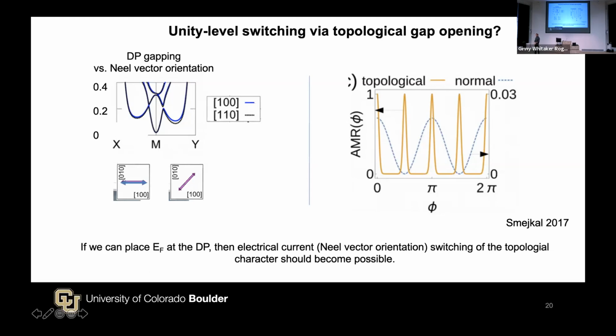From what you're saying, these different layers, does that mean that the controversy over whether the surface of manganese bismuth telluride is gapped or gapless is no longer a controversy? It could be entirely explained by which surface people were looking at? The main controversy in gapped versus ungapped is on the 124 compound, and there's only one type of surface on that. There is still controversy whether it's gapped or not. What I would say from the two slides I showed you is that I think the real case is somewhere in between. I think there are gaps to the surface states, but they're definitely not as big as we would like. And the temperature dependence as you go across the Néel temperature is also not what you would really like to see. So we'll be putting out a detailed paper, but it's not as fun as you would like.